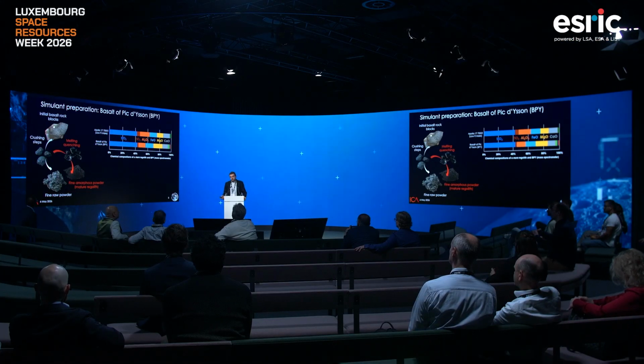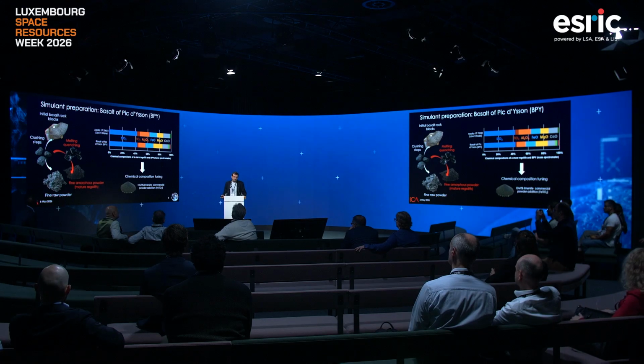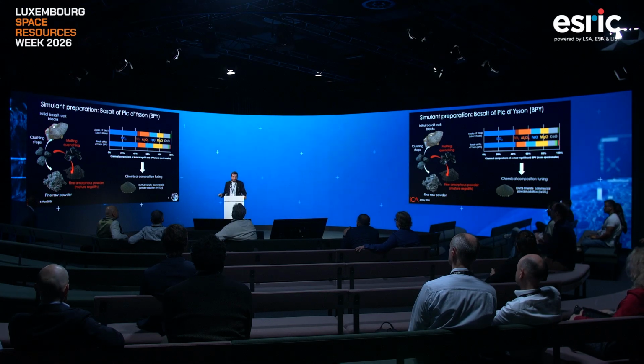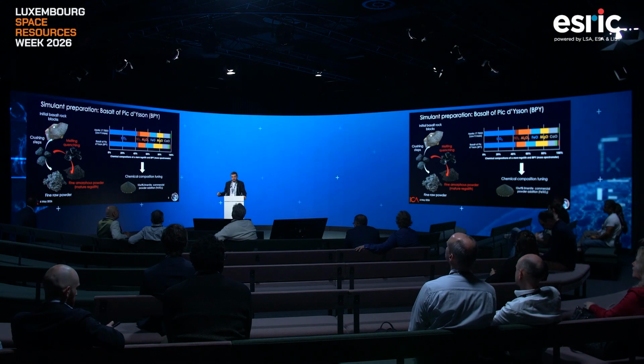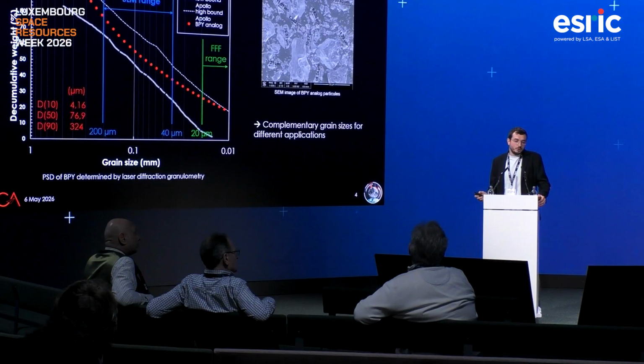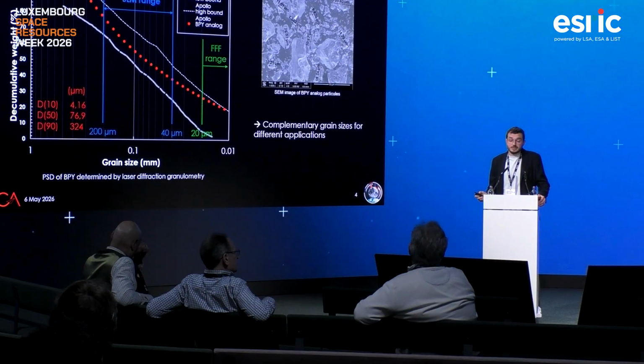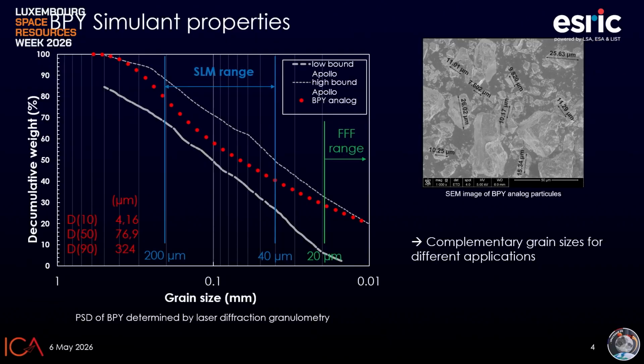As you can see, it's expected, but since we are using a basaltic rock, we have a chemical composition close to a mare region regolith. Since we are quite low on titanium dioxide, if the aim is to see the effect of the titanium concentration, we can also add some ilmenite powder. Here you have the grain size distribution of our powder in the end. It's really nice for us because depending on the process we'll be using, we can separate this grain size distribution into some ranges. Below 20 microns, we use it for the fused filament fabrication process. And between 20 and 40 microns, we use that for selective laser melting, for flowability reasons, mostly.